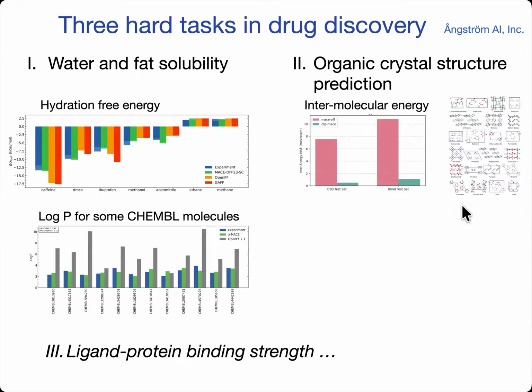Moving on to crystal structure prediction, this is where we need to make specialized models. So these are not the same model that we use for hydration and solubility, but you take small molecules. These are not yet drug molecule size, but just very small molecules which have standard crystals that have been accurately characterized. And we focus on modeling the intermolecular energy, and the red bar here is in milli-eV per atom, the intermolecular energy accuracy of this MACE-OFF model, the one with which we did the hydration. And these errors are not really good enough to distinguish between polymorphs, because intermolecular energies are much smaller. But if you make a bespoke model that targets the intermolecular energy, then you can get these very, very